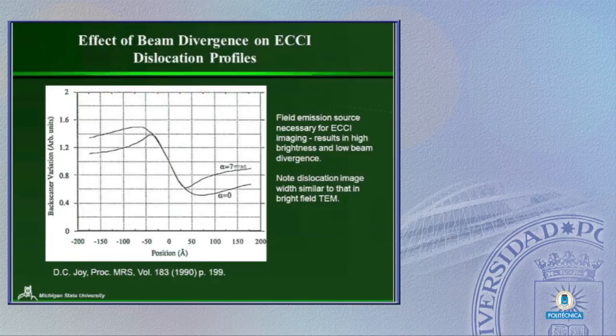Here's some theoretical work by David Joy about 20 years ago that shows some dislocation profiles as a function of beam divergence. You can see the peak to background decreases as the beam divergence increases, and if you get much below this, you end up getting a real flattening. You really can't image your samples well at all.